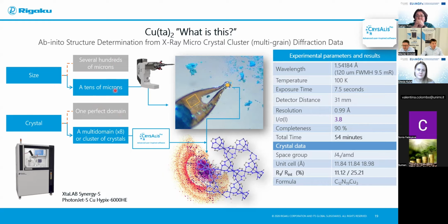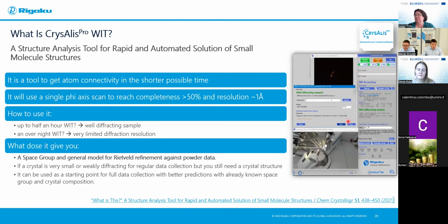This is also an example where I just measured a cluster of the powder, basically. You can see I mounted it on the loop. This yellow thing is 100 microns, as indicated on this loop. I took a small amount of material and performed what is called a What Is This experiment. It took me an hour to measure it, but it was enough to get the crystal structure solution from it, which you can then use to bootstrap your Rietveld refinement on the powder.